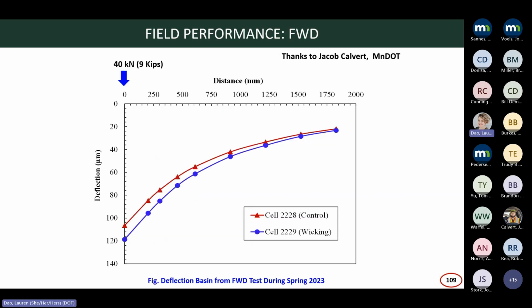So after that, we also conducted the FWD test. Thanks to Jacob for conducting this test and sending us the data. So for the FWD test, as you know, we have 3 drops, and we are plotting this deflection basin with the second drop, so 40 kilonewton load, 9 kips. And what we are seeing here is that in the control section, we are having less deflection in terms of the FWD results. So that's interesting because the wicking section was draining out the moisture. It was showing us less settlement. But in terms of FWD, when we are seeing the results, we are seeing a variation in the D0 of 10.2%. The control section is having less deflection from the FWD results.